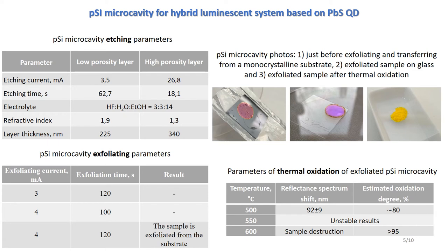The manufacturing parameters were selected in such a way that the samples preserve the morphology of the structure and their integrity as much as possible. The exfoliated freestanding sample is a thin film no more than 15 microns thick, the surface of which, after thermal oxidation, becomes slightly uneven and bumpy due to internal mechanical stresses from the growth of an oxide layer on the silicon pore walls.